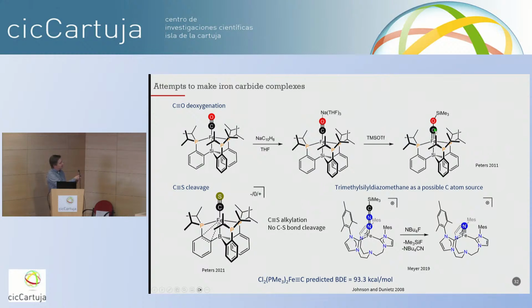CS has a weaker bond, and so this is often proposed as a way to make carbides. Again, in Jonas's group, they were unable to break the CS bonds. And then you could think about using ligands such as trimethylsilyl diazomethane, which you could lose N2. You could probably desilylate with a fluoride source. But these, for Karsten Meyer's group, and we've done similar chemistry, they only make nitride complexes.